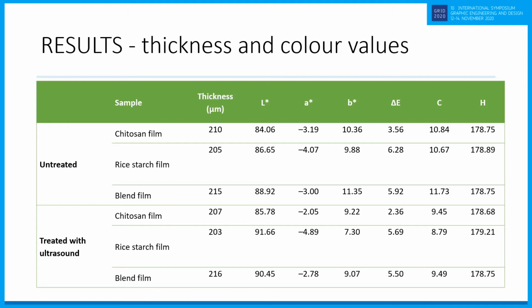If we look generally, color is an important factor of the appearance of packaging materials. So the total color difference, chroma and hue angle were calculated from the color values. The untreated chitosan films were more colored than rice starch and blend films. It is known that chitosan has more yellowness compared to other tested samples in the research. All films also include plasticizer, which also affected the color. The hue angle was not significantly different among all sample films. The results of calculated chroma showed that the untreated samples have more yellowness than the treated ones.